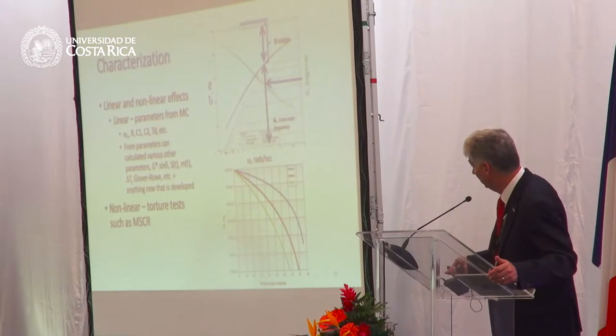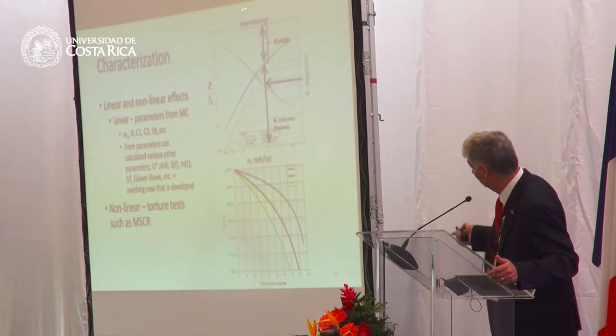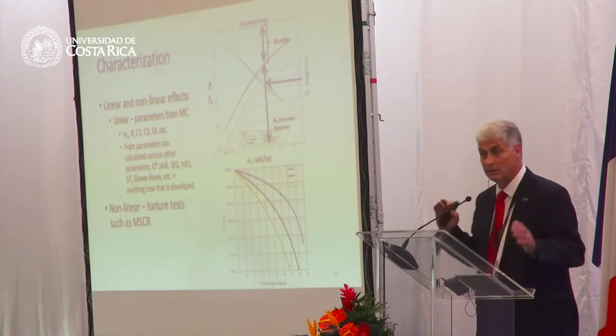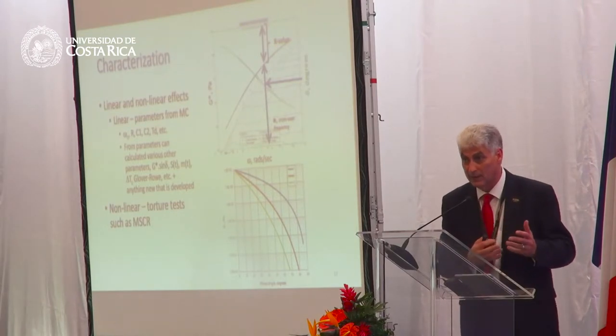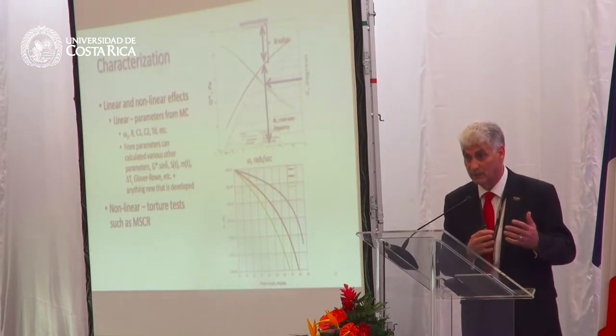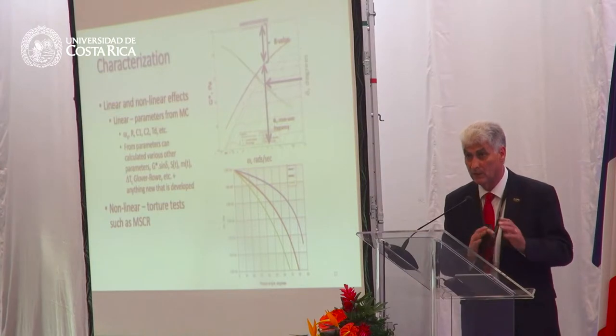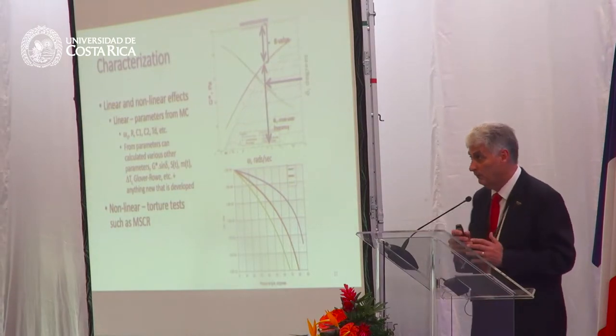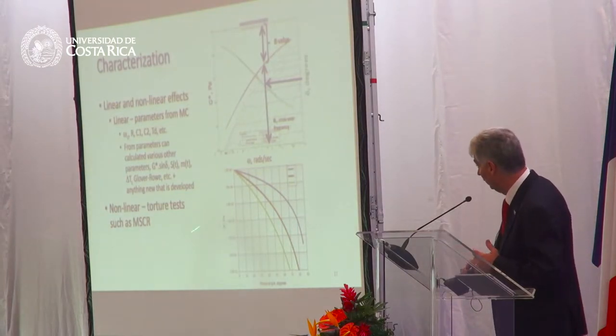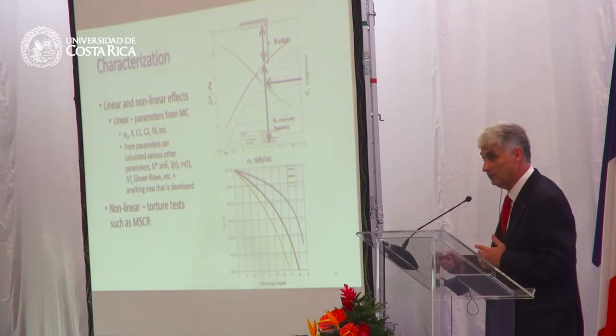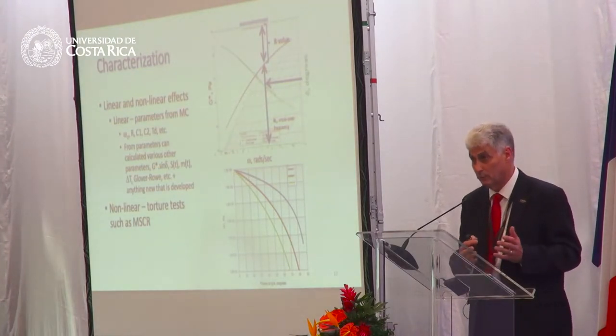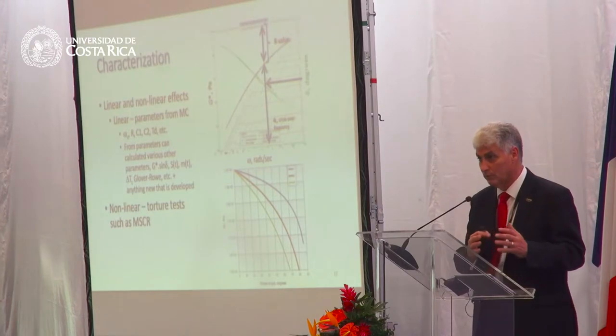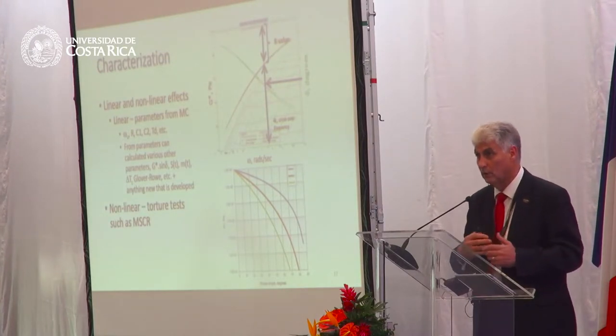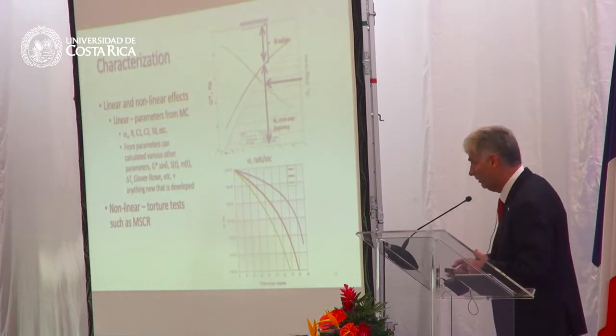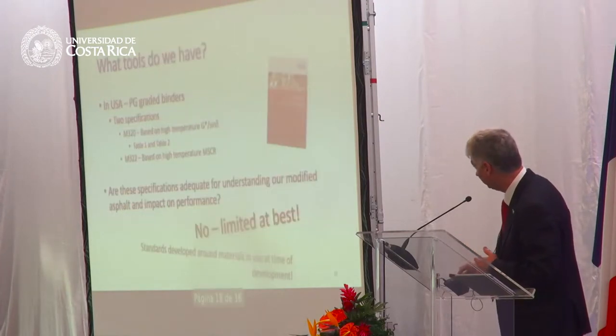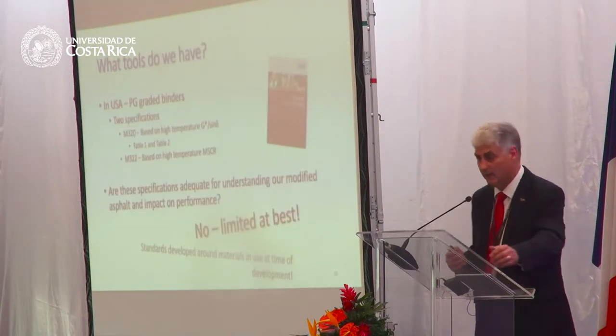One other thing I want to mention before we go on is that this is all in the linear domain. This is really dealing with things like cracking and performance at reasonably high traffic speeds. When we need to consider permanent deformation, we really have to go to the nonlinear domain to consider tests such as the multi-stress creep recovery test. So we can't always rely on tests in the linear region when we're looking at deformation and permanent deformation of asphalt mixes.